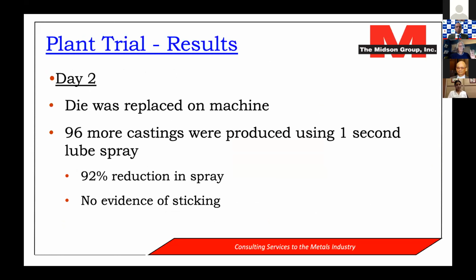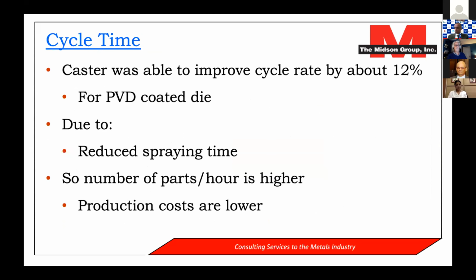And so on day two, the die was replaced, and 96 more castings were produced with this 1 second lube spray. That's a 92% reduction in spray. And again, no evidence of sticking. So we didn't quite get to lube-free, but pretty close. And there were some other benefits that we observed from using the low level of spray.